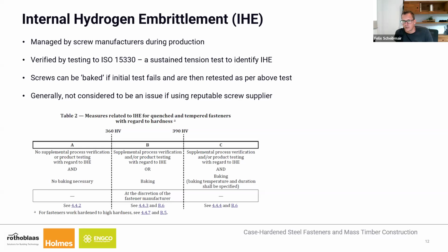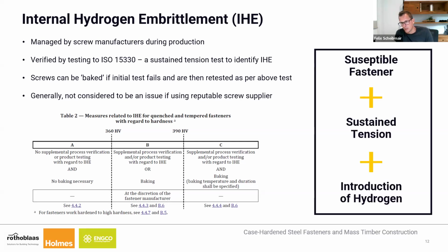As screw manufacturers, that process can be managed during the production cycle. So, for example, by adding some inhibitors into the acid wash, by looking at how the electroplating process is done, and also by doing some verification testing to check the level of hydrogen, or to check that there are no initial failures. You can see down the bottom there, it still depends on the fastener material somewhat. So you've got the hardness still coming into play here.